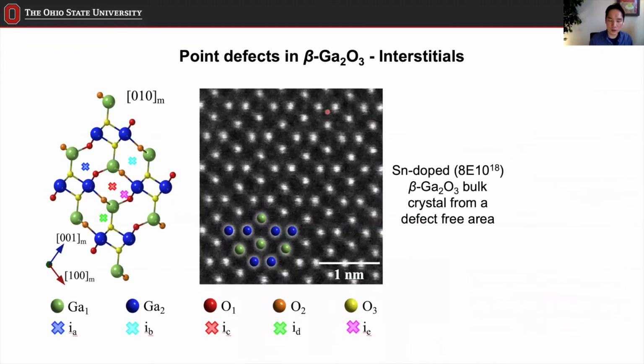The first sample we looked at was the bulk gallium oxide. This is like the substrate. We didn't start with the film first, because we had the bulk substrate. We started with that first, and the bulk substrate was doped with tin atoms. This is the doping concentration, nearly about 10 to the 19th, which is pretty high. We are looking at an area where not much is happening. So this is a regular area.